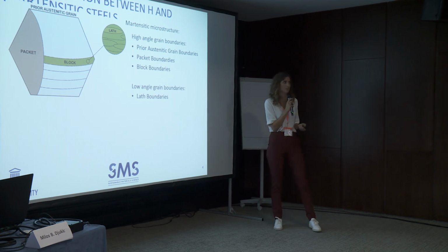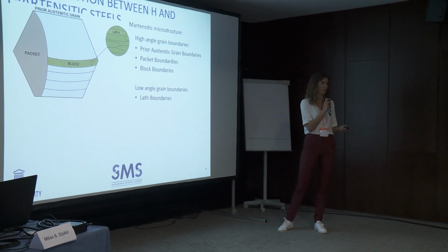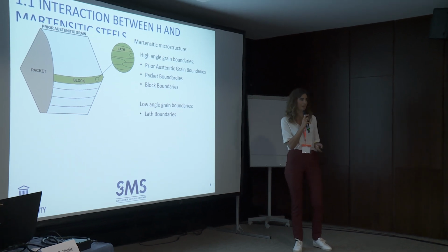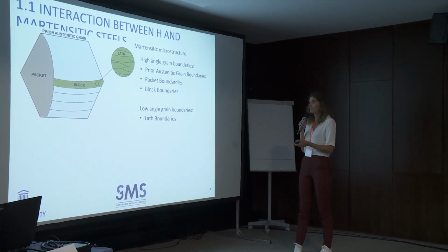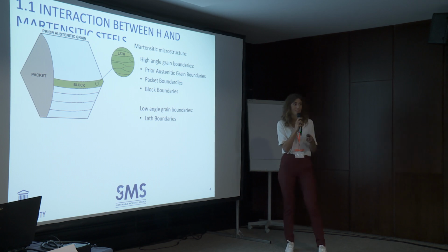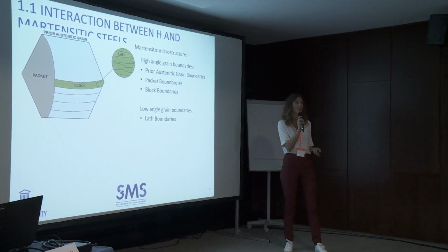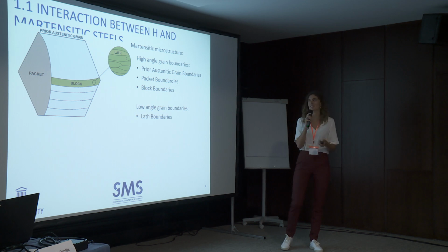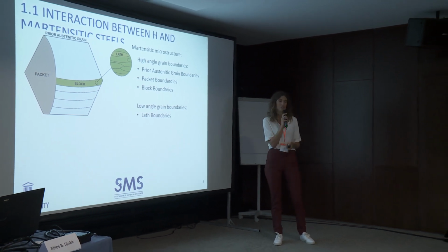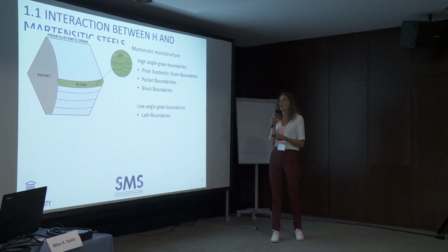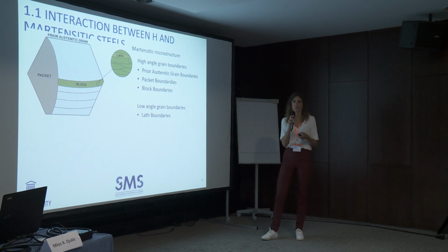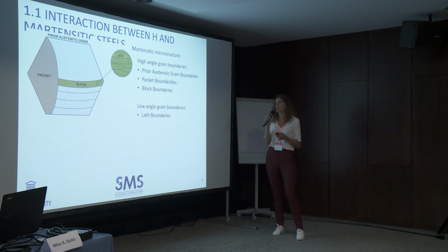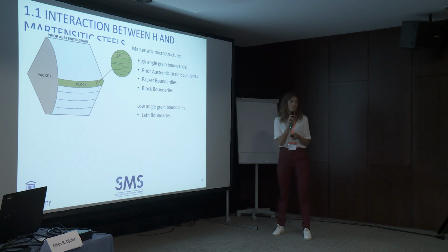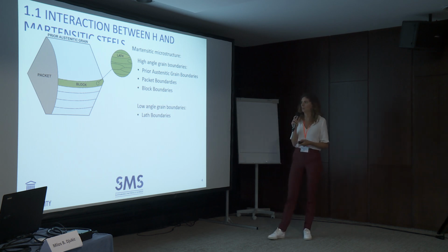So how do martensitic steels look like? I suggest most of you already know that, but it's in fact a quite complicated microstructure. You have a parent austenite grain. This can be subdivided into martensitic packets, which can in turn be subdivided into martensitic blocks, which also consist of martensitic laths. All these specific substructures have specific boundaries. We have high-angle grain boundaries, which contain the prior austenite grain boundaries, the packet boundaries, the block boundaries, and the laths are surrounded by low-angle grain boundaries.